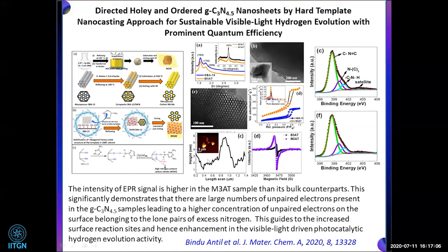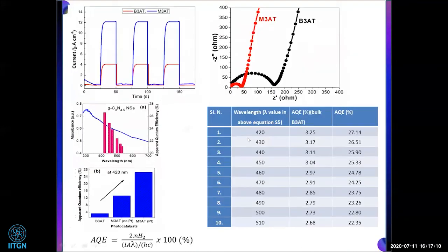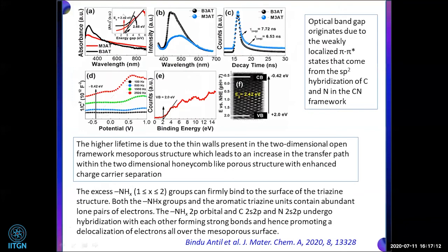So this decreases the band gap. Generally we know the band gap of this material used to be 2.7, and we reduced the band gap to 2.42 electron volt. So that is a very good thing. And one more important thing is that this is a very thin wall structure, and because the path length increases, we have a very high separation of electrons and holes.